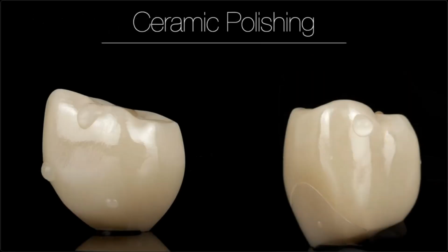And ceramic polishing is a great option, especially for the subgingival portion. This is polished zirconia, and you can see the very low surface energy there. That water on there just kind of balls right up. So plaque debris doesn't really adhere that well to it. And then the tissues love it. You even get a hemidesmosome-like attachment to it. So you get a very good peri-implant seal. Some very healthy gums.